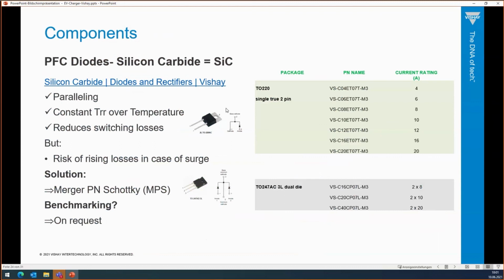Very important. We have silicon carbide diodes since about 1 year. So with silicon carbide, it's nice. You can do paralleling. You have a constant TRR over temperature. You have reduced switching losses. But when you have a surge current, so a very high current going into the system, you will have a much higher forward voltage drop. So this is just by nature. So what we do, we have merged PN Schottky diodes. So there's a PN structure inside as well, which makes the part more robust in case of surges. We have some benchmarking, but I don't want to disclose it here. So please feel free to ask us afterwards and we can share everything with you.